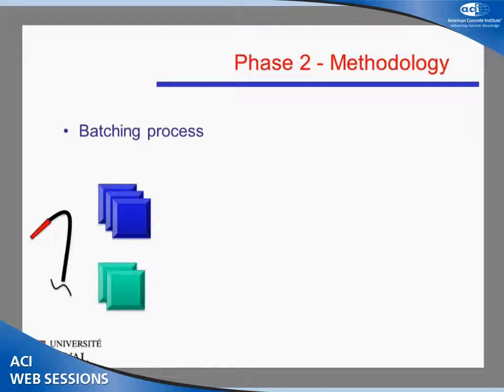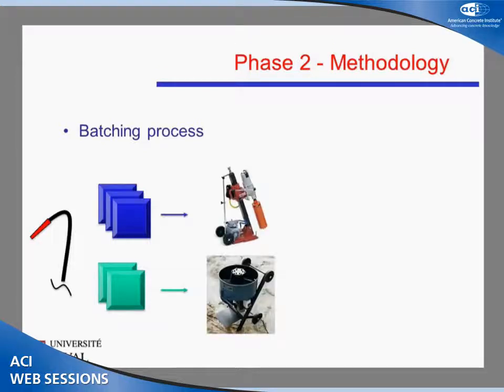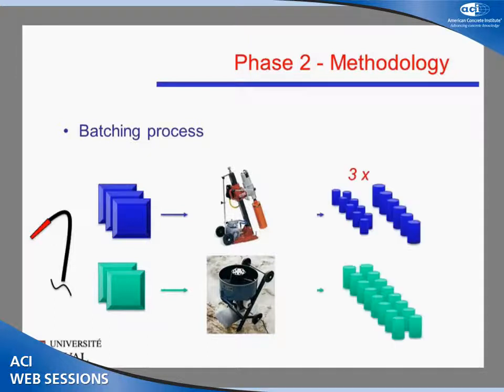So what happens? We shoot 5 panels. For all the mixes considered, we shoot 5 panels. 3 of the panels are cored. 2 of the panels are actually sampled directly from these panels, avoiding essentially about an inch from the bottom. We don't want to have too much paste in it. We want a representative sample. And so the 2 panels that we sample, we put into an 80-liter planetary mixer. This provides a lot of samples to test with. Essentially, for the cores, we want to have 3 panels, so 3 sets of samples to test. And that's actually very interesting for dry mix because there is some variability in dry mix. We want to evaluate that.